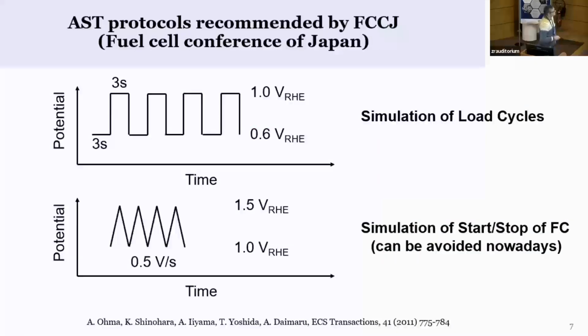Then we, or the field, try to have stress tests that are more unified. And in Japan, they introduced a procedure to test these catalysts. One test is a load cycle test, so that you simulate the load of a fuel cell cathode, where you go from idle, so no reaction, to an electrode potential where you have oxygen reduction, and you just jump back and forth many times between these two potentials and see what happens.